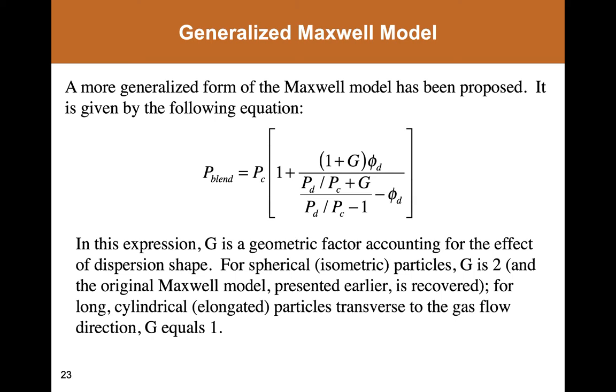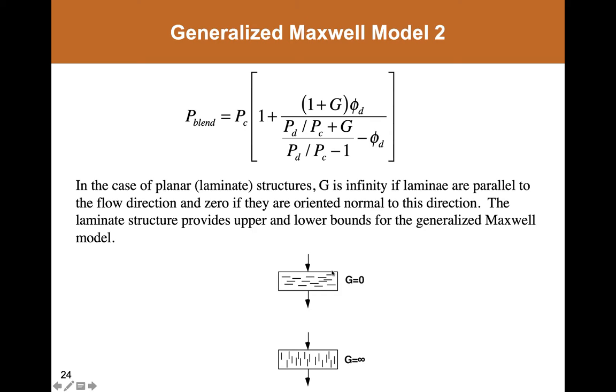The original Maxwell model is recovered when G is equal to 2, that's for spherical particles, and when G is equal to 1, this corresponds to long cylindrical particles that are oriented transverse to the gas flow. Other values of G, such as G being equal to 0, corresponds to a laminate structure that's oriented perpendicular to transport, and G being equal to infinity corresponds to a laminated structure where the laminates are oriented parallel.